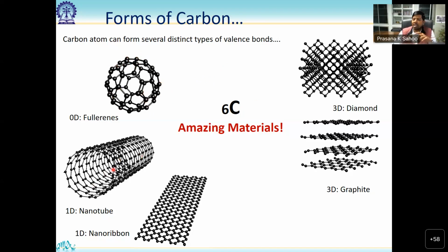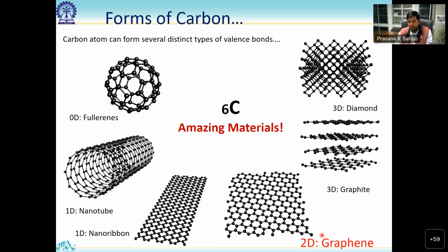Or we can form carbon nanotubes. There was a time this was a very hot topic. A carbon nanotube can act like a tube of a few nanometers diameter that can give ballistic transport, because carriers can go from one end to the other without any scattering. So it can be ballistic transport. Then came the Nobel Prize with graphene, a single layer of carbon, and because of this it is sometimes called a Dirac material. The valence band and conduction band touch at a point, so carriers can transfer from conduction to valence band without scattering. That can give ballistic transport.